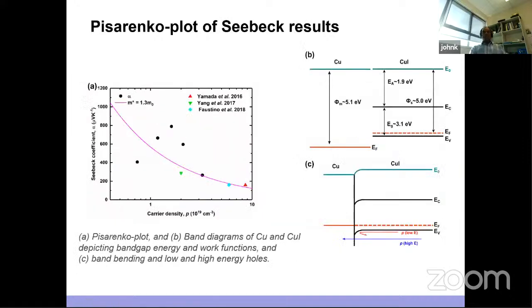So we tried to explain this with what's called a Pisarenko plot, which is basically for energy filtering, plotted based on the assumption that the effective mass is 1.30 times m0. So what you see here is something called the energy filtering effect. You can see the deviation of the Seebeck coefficient from the single parabolic band model. So there is the energy filtering effect and energy dependent charge carrier scattering at the interface and grain boundaries. And that's what you can see from the band diagram. It nicely explains that there is a sort of energy filtering effect due to the carriers' movement.